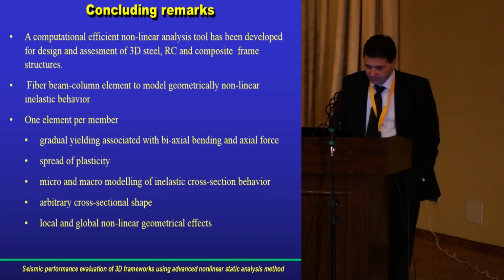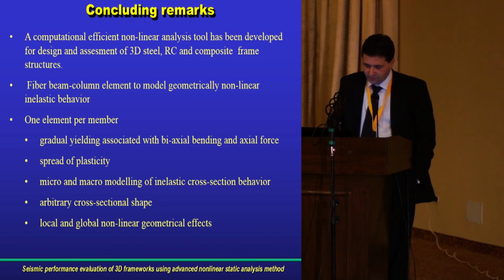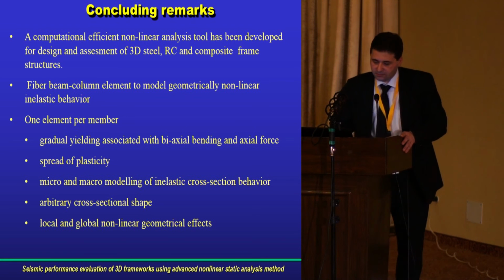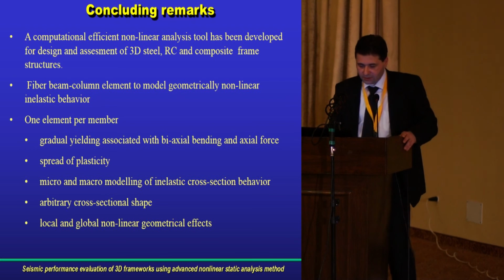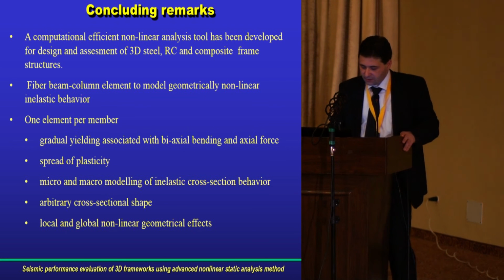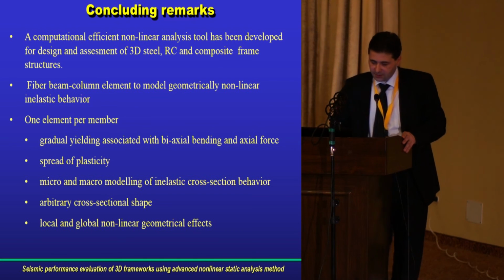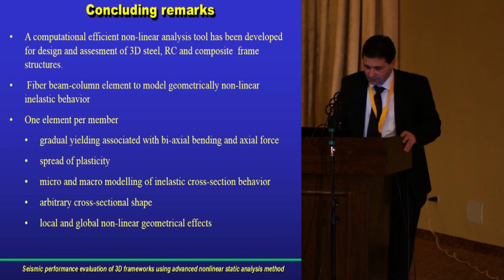Concerning the nonlinear analysis of frameworks, we can model the nonlinear response by only one fiber beam-column element to take into account the geometrically and inelastic behavior. We use only one element per member, and it is allowed to consider gradual yielding associated with biaxial bending and axial force, gradual spread of plasticity. We can model at the micro and macro level the inelastic behavior of cross sections, either using fibers that take into account explicit nonlinear constitutive equations, or modeling the inelastic behavior of cross sections through analytical force-strain relationships. Also, local and global nonlinear geometrical effects can be taken into account.